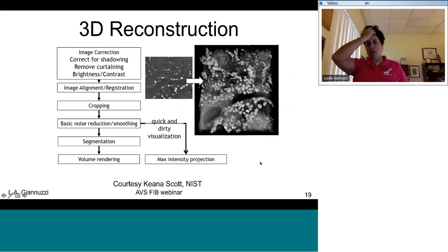Okay, so how do we do 3D reconstruction? Again, there are sort of image correction things that you can do. You can correct the shadowing, you can remove curtaining, although I'm not a big fan of how that's done, but I'll leave that for another day. You can control brightness and contrast. There's the image alignment and registration, which, as I mentioned, is best done with a fiducial mark. There's cropping, there's basic noise reduction and smoothing, there's segmentation, there's volume rendering, there's quick and dirty visualization, maximum intensity projection. And again, all of this can take many more hours than the actual acquisition of the 3D data in and of itself.